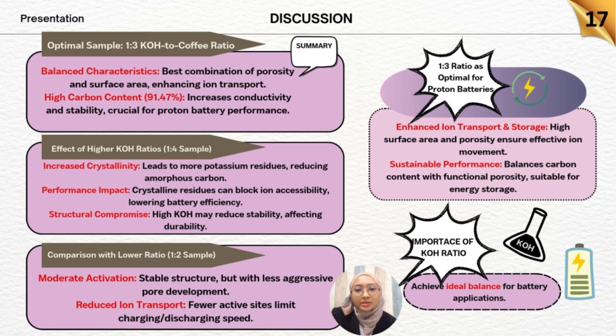So, the importance of KOH ratio. Fine-tuning the KOH ratio is essential. Our results show that the 1 to 3 ratio provides the best combination of structural stability, porosity, and carbon purity, making it highly effective as an anode material.